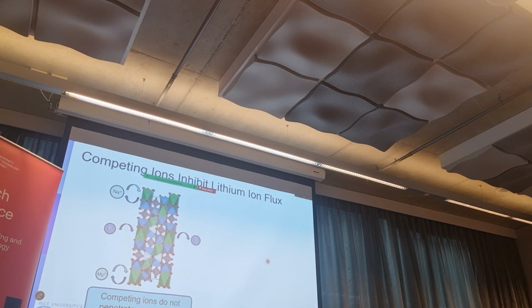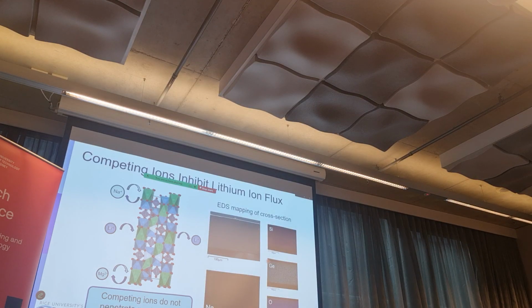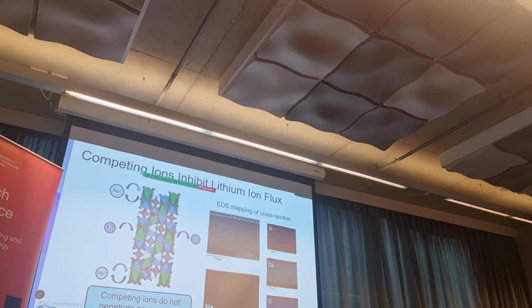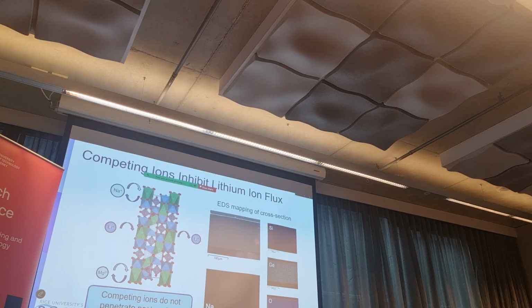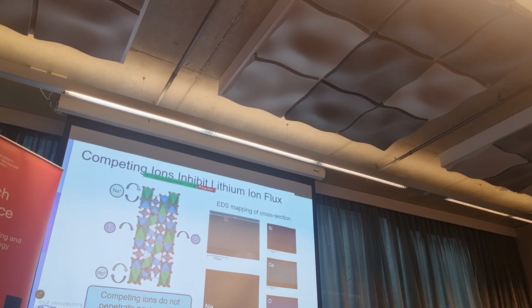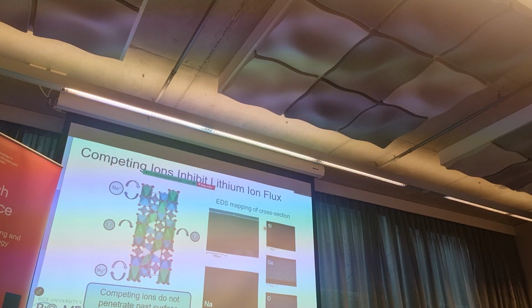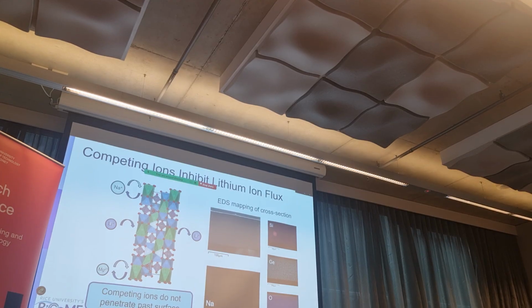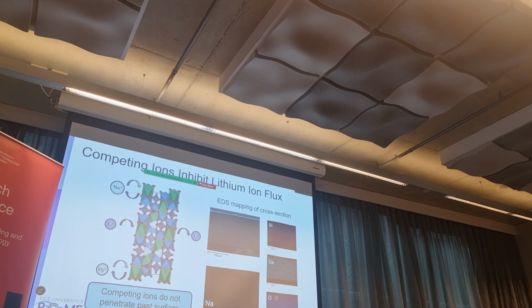We can also verify this by doing EDS mapping of the cross-section of the solid state electrolyte after the experiment. This is the solid state electrolyte, this is the top layer, just when you don't have any sodium. Inside, we see the composition of the solid state electrolyte—you have a lot of silica, germanium, oxygen.